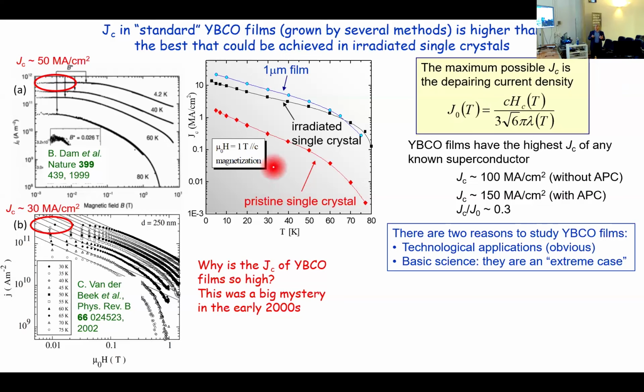And these are 2 early studies, one by B. Dam, 1999, the other by Van der Beek in 2002, showing values in the range of 30 to 50 megaamps per square centimeter, just in films that they grew without trying to introduce any additional pinning. I don't have time to go into details, but that was the big question in the community, a big mystery. What was the reason for the very high critical current density in YBCO films? Nobody knew at the time.